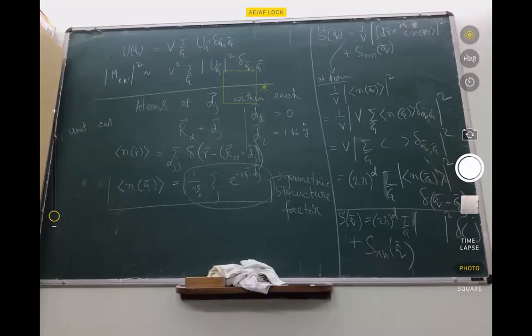And so basically, in an ideal crystal, you expect S of Q to be non-zero and like delta functions at the reciprocal lattice vectors, but thermal fluctuations, quantum fluctuations, and defects would generate finite widths in these delta functions. So when you look at scattering data, you won't find absolutely sharp peaks. It never happens in reality at reciprocal lattice vectors.